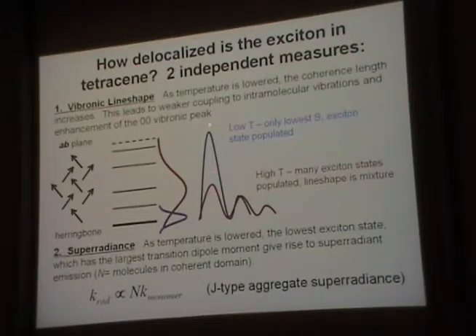And in this case, the 0-0 peak, this is a vibronic progression or an exciton-phonon progression. You think of these little bumps as phonon sidebands, I guess, if you're a solid-state physicist in the audience. The 0-0 or the zero phonon band becomes hugely pronounced in these molecules, or these aggregates, because you're condensing into a state that has very, very weak phonon or vibrational coupling. This is not technically a phonon, it's an intramolecular vibration. But for the purposes of the Hamiltonians, which is all that we really care about when you talk about spectroscopy, it's a phonon, it's whatever you want to call it.